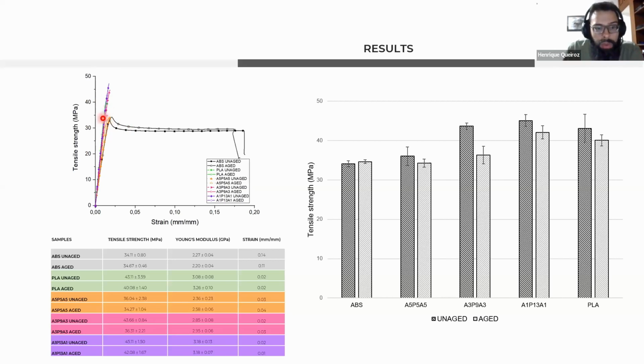But down here, we have all of our hybrids. And the first thing that we notice is that the behavior is very, very similar to PLA. So the brittle failure of the core was dominant, right, when it comes to the behavior. And the tensile strength was all very similar and, of course, lower than the neat PLA, which was also expected.